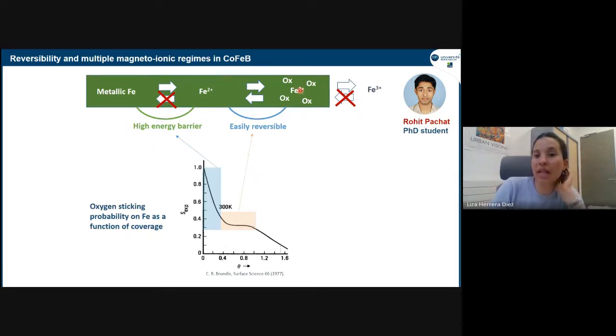So this is really the part that we think is reversible. We think that there's no change in oxidation number from Fe2+ to Fe2+. Here it's just that the surroundings of the Fe2+ have more oxygen, but not necessarily the iron. So this probably has a much lower energy barrier to actually go back. And this is really what we see. This part seems to be a lot more reversible, or reversible with lower energy barriers with respect to this. However, I didn't show it, but if we overdo the oxidation, then we do end up in something that we cannot come back from. And this is more probably related to this part. Also, they say that they end up with Fe3+ at the end of the process. So this is something that I didn't show, but we also know that at some point it's just too oxidized and it never comes back.